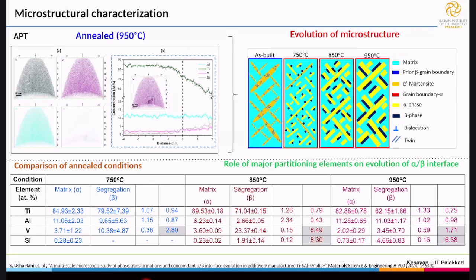Based on this, we propose how the microstructure evolution takes place in 3D printed titanium 6 aluminum 4 vanadium alloy. You can see that the as-built material has a lot of segregations, and the dislocation density is high. Upon heat treatment, those dislocation regions act as sites for the nucleation of beta, and beta comes out from the solid solution, and the size of the beta increases.